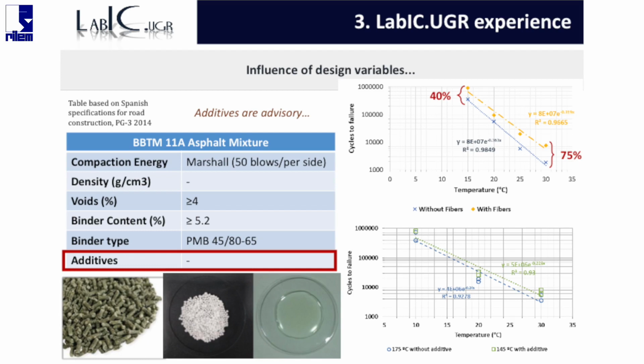But definitely, if you use additives in the material like fibers, you can drastically increase its mechanical performance and its service life. Also, if you use other types of additives like waxes or surfactant materials, you can reduce the manufacturing temperature of the material and still obtain a good mechanical performance, because the material improves its workability and it can be densified in a better way.